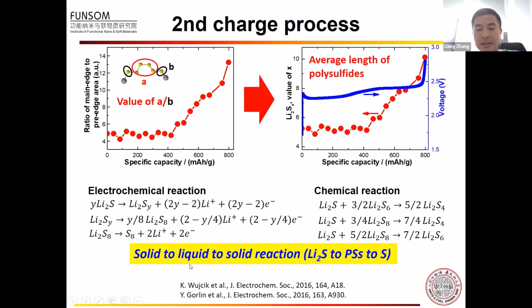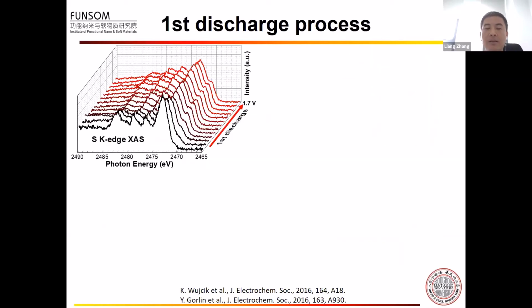So these results clearly indicate that the second charge process is not a two-phase conversion reaction, but a solid to liquid to solid reaction, which means lithium sulfide is first converted to polysulfide and then to elemental sulfur. But the question is, where does the polysulfide come from at the beginning of the second charge process? Because in the first charge process, there's no polysulfide. To understand this, we also record the sulfur K-edge spectra during the first discharge process.